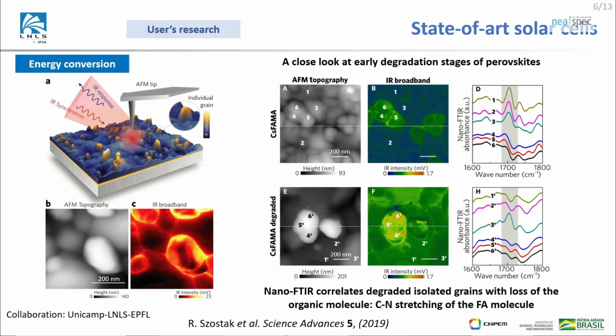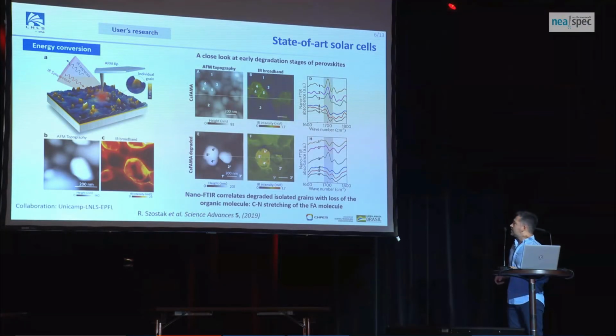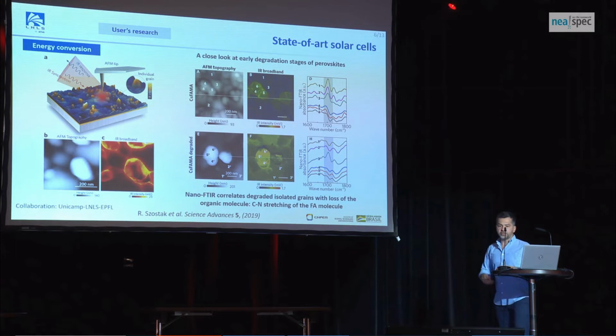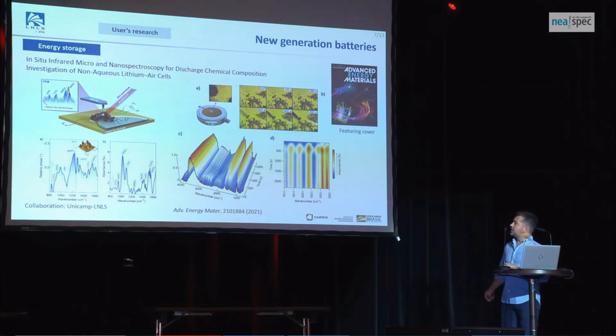We took spectra on those and also outside, and we could see that the signal here in this CN stretching mode is very different. And we also induced some degradation, so we exposed these films to very intense white light, and we could see that this degradation is actually changing a lot here. So the conclusion here is that these early stages of degradation happen sort of grain to grain, so it's something that helps people to develop this new material. So this is another example.